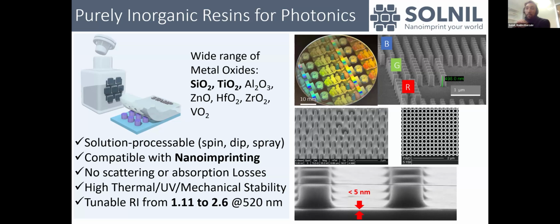Since our materials are purely inorganic, they have the advantage of being highly stable with temperature, UV, or mechanical stress. They can also withstand high humidity. And one of the distinctive features of what we do is the control of refractive index. So we can go from very low refractive index, 1.11, up to 2.6 for visible light, which is quite unique.